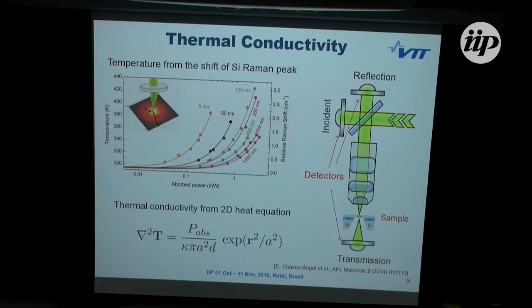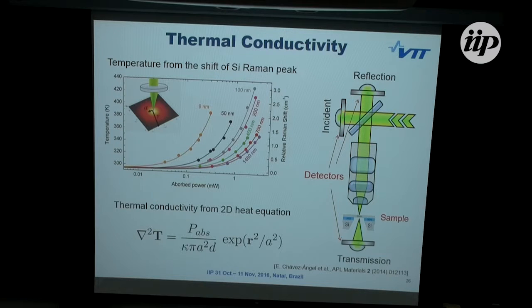So now the thermal conductivity. I mentioned already that the Raman peak, this 520 1 over centimeter wave number, shifts when the temperature is changed. So this is a measurement setup. The sample is here. The exciting light comes here, and then there is a set of detectors that measure the power. There's one to measure the transmitted power, one for the incident light, and then the reflected power. So when putting these together, one actually knows the power absorbed into the membrane.